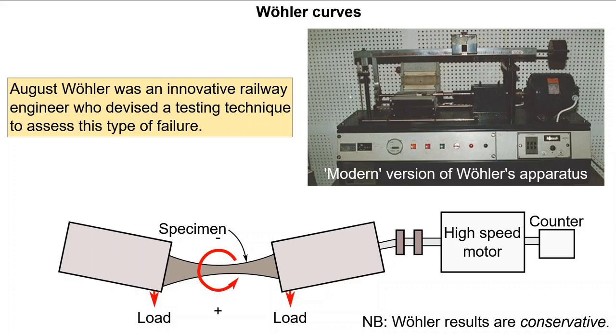He devised a methodology to check the number of cycles to failure for a given component loaded under the same conditions as the railway component. The system operated on the basis of a loaded component as depicted, which should then be spun at a high rate and the number of cycles to failure tabulated. The specimen would have half of its gauge in compression and the other half in tension at any given point in time.